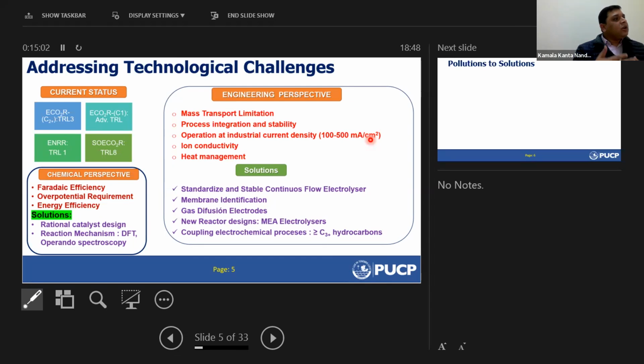To get better mass transport, we can use an electrochemical flow cell. In an electrochemical flow cell, the geometry of the cell allows us to operate at higher current density. And again, when we operate at higher current density, we produce a lot of carbonates near the surface of the electrode, and that destroys the PTFE hydrophobic coating on these gas diffusion electrodes, and it causes electrode flooding. Suddenly, your current density drops after 200 or 300 hours of operation. So every time you cannot change the electrode and go for an industrial scale production by electrosynthesis. So we have to also think about a proper gas diffusion electrode.